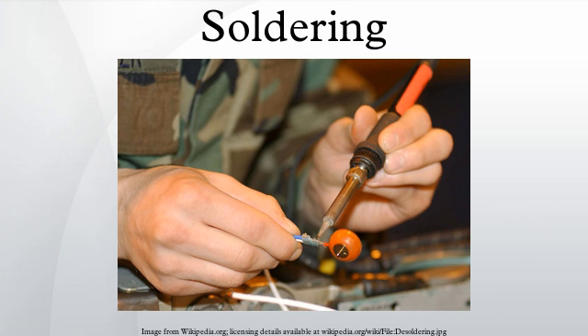In brazing, one generally uses rods that attach to the joint while being heated. With silver soldering, small pieces of solder wire are placed onto the metal prior to heating. A flux, often made of boric acid and denatured alcohol, is used to keep the metal and solder clean and to prevent the solder from moving before it melts. When silver solder melts, it tends to flow towards the area of greatest heat. Jewelers can somewhat control the direction the solder moves by leading it with a torch. It will even run straight up along a seam.